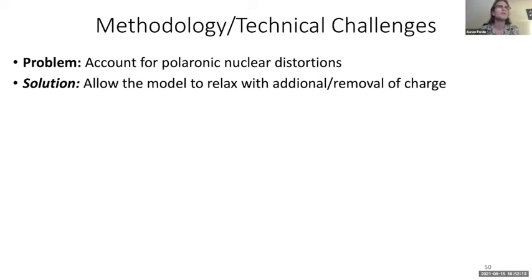And then once you add or remove those charges, you allow the model to optimize around the new charge configuration, which should give different structural characteristics. And so that was the methodology of how we described polarons for this paper.